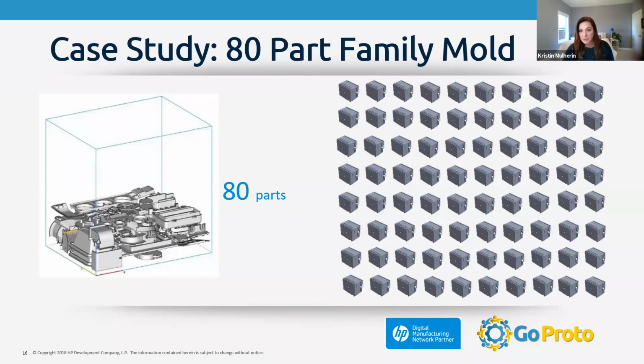With that in mind, it looks like we've got a couple questions regarding design. I think you touched on it earlier about the pin needing quite high resolution. What are the resolution and tolerances that can be achieved with MJF? It's something that you can print, measure, and get better, just like when you're making an injection mold. You'd run it multiple times, measure items on it, and tweak your design to get better tolerance outcomes. Out of the box, it comes down to about plus or minus 20 microns, and I think it's a percentage over a certain length, because different lengths have different tolerances. But it's an iterative process where you measure and get feedback and improve.